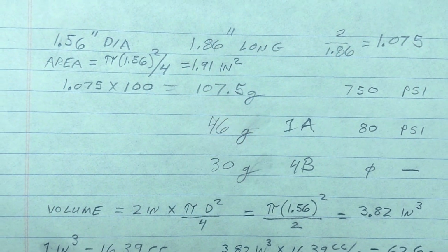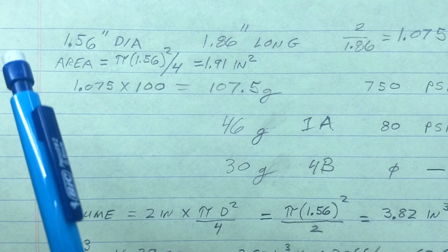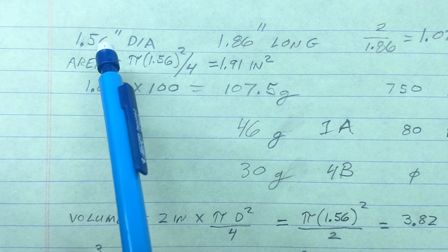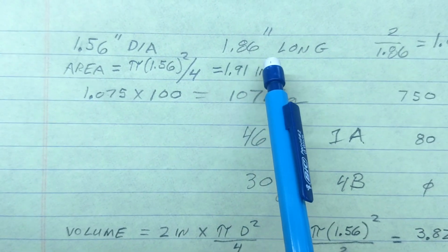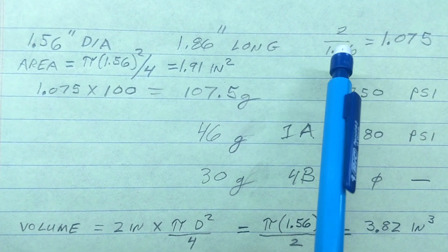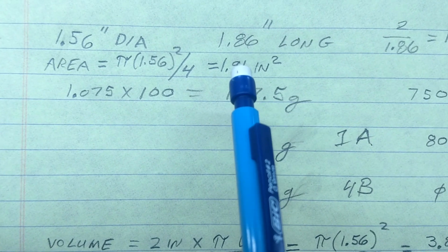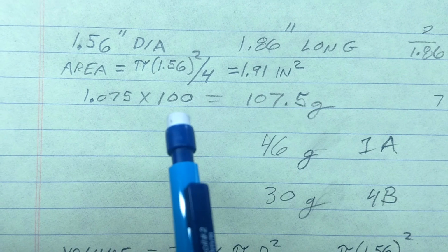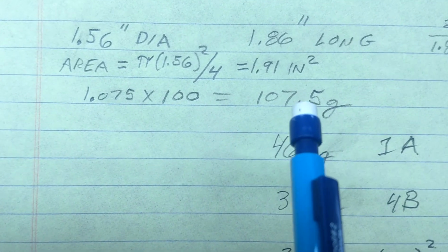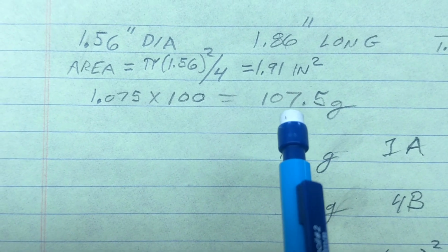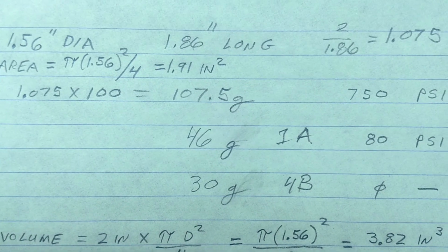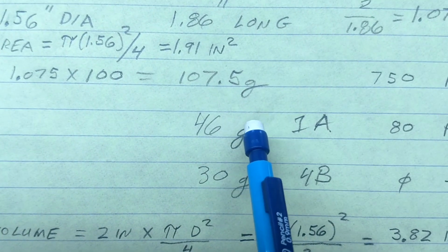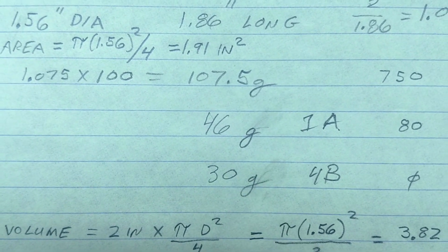Okay, here's a summary of what we just did. We found the diameter of our samples to be 1.56 inches. The one that I trimmed to square up the end came out to 1.86 inches, so it was 7.5% short. So the area of our sample is 1.91 square inches. So the equivalent weight, if our basic mix sample had been the full 2 inches long, it would have weighed 107.5 grams, whereas it weighed 100 grams actual. The other two samples weighed 46 grams and 30 grams, respectively.